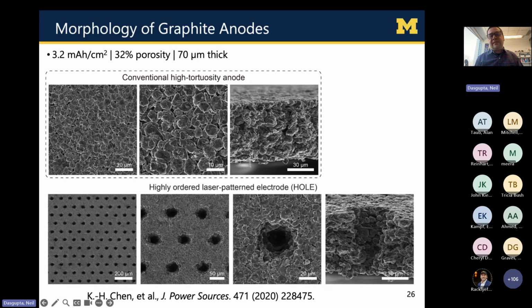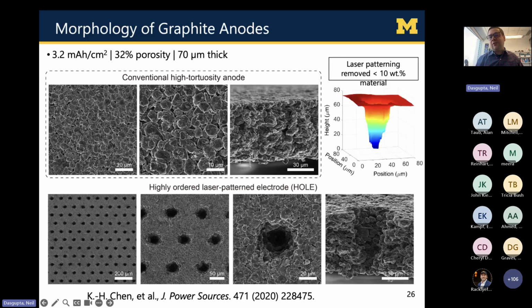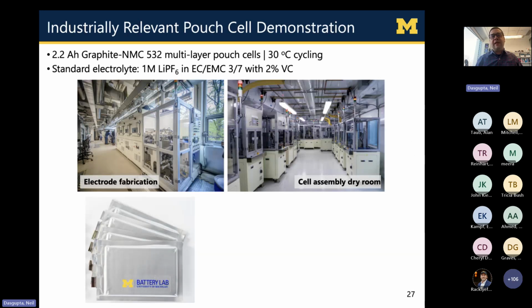And then you can see the picture of what happens after we've drilled the holes with the laser. We create these beautiful hexagonal arrays of holes, and these are channels, as you can see in the bottom right with the cross-section, that go all the way through the thickness of the electrode. And we can image this cross-sectional profile to see that indeed we have been able to successfully create these holes. HOLE is an acronym we also use, highly ordered laser patterned electrode, that can facilitate this improved ion transport. I want to also mention that throughout the rest of my talk, all of the data I'm going to be showing you are on industrially relevant pouch cells. So these aren't just small coin cell batteries made in a glove box manually by a graduate student. Here we're leveraging the battery lab facilities.